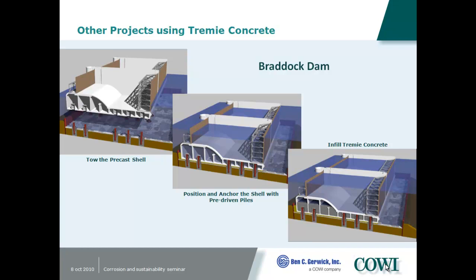Instead of using a lift-in type of approach, Braddock Dam on the Monongahela River for the Pittsburgh district was a float-in type of shell where they used these maintenance bulkheads to provide buoyancy, and then floated over drilled shafts with a pintle type of connection. They used Tremie concrete in there just to get a seal, and then they went in the dry and placed the rest of the concrete in the dry.